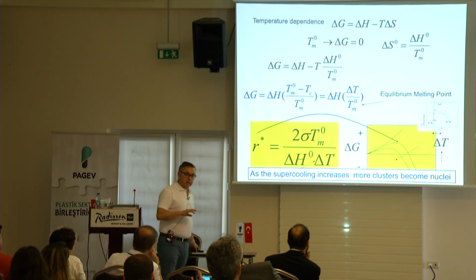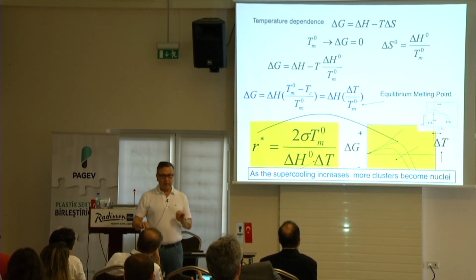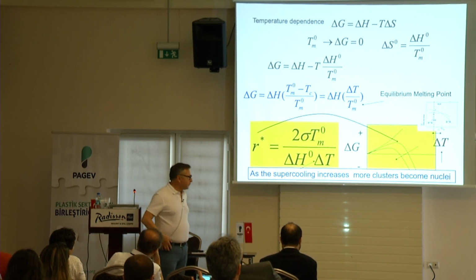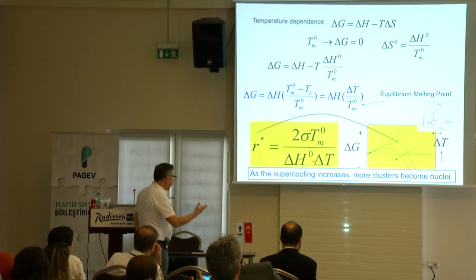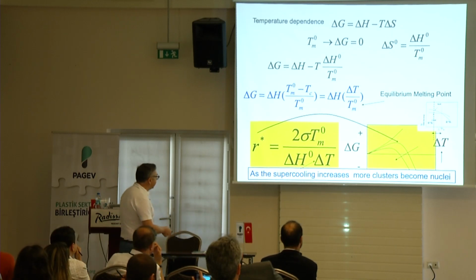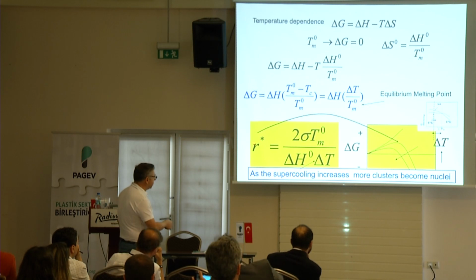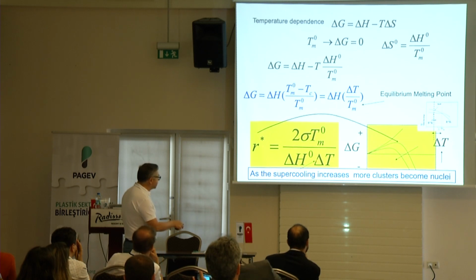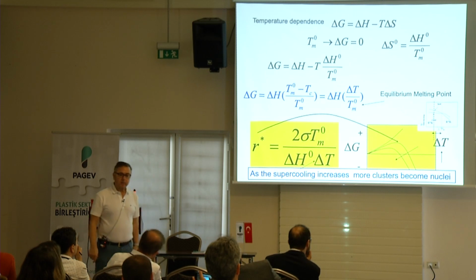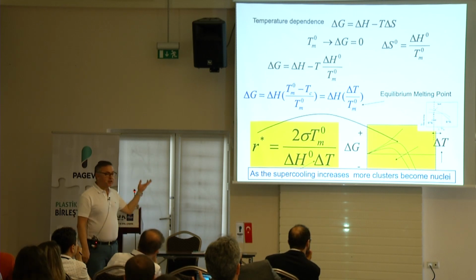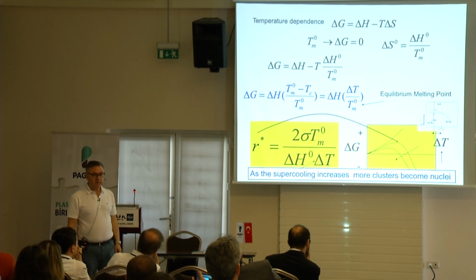And this is where the thermodynamics connects to the injection molding shop, okay? That size, that equation. Where does it connect? It connects with this: critical size and delta T. This doesn't change much. Surface tension doesn't change. What really is connecting is the critical size to supercooling, meaning how far away you are from your equilibrium temperature. Delta T, this is delta T. Okay? What does it tell you? The larger the delta T, the smaller the critical nuclei size.